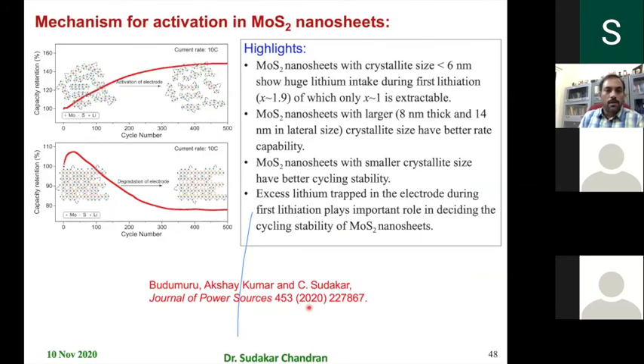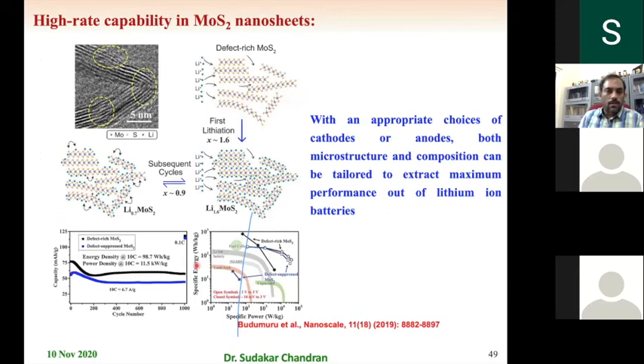So just to summarize this, the excess lithium trapped at the defect sites plays an important role in deciding the cyclic stability in MoS2 electrodes. Therefore, it enables a high rate capability in the material. This particular Ragone plot shows that if you have defect-rich, the specific energy is higher, and you can also have the specific power higher. Defect-suppressed ones always have somewhat compromised values.